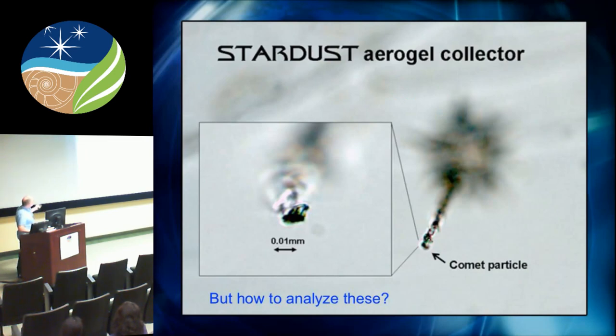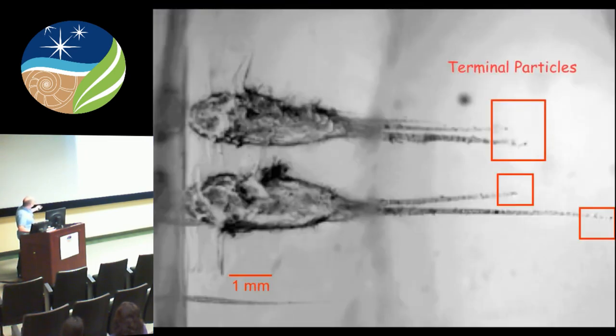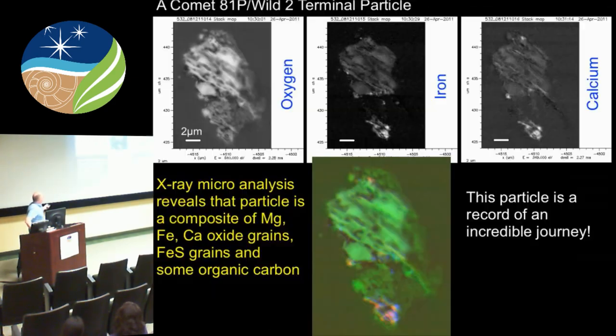So here's, again, some terminal particles. Here's the edge of the aerogel. You see the particle comes in, sort of explodes, and the terminal particles project down to, say, several millimeters into the aerogel collector. And so the terminal particles turn out to be pretty interesting for their inorganic chemistry. And so here we're mapping oxygen, iron, and calcium using the scanning transmission X-ray microscope. And here's a composite. So you can see lots of oxygen. You can see the little blue bits here. These are iron sulfide grains, which is fascinating. And then there's a calcium-rich region down here.